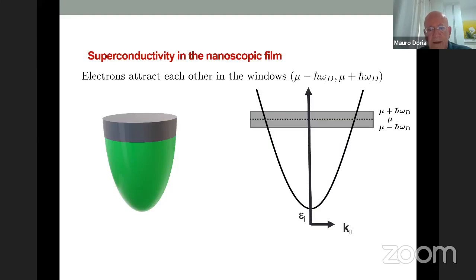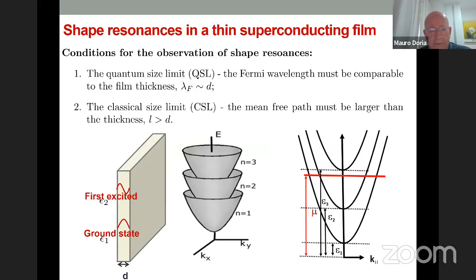So that's the reason why you have those jumps in the temperature, because you have the Fermi energy. This is along the discrete direction. You have the Debye strip, and this is where superconductivity is. And now if you have discrete levels, you begin to have a Fermi surface that crosses some discrete energy levels. And then according to the parameters, as you change the thickness of the film, you can have more parabolas under the Fermi surface, under the chemical potential. And that's why you have these jumps in the critical temperature.